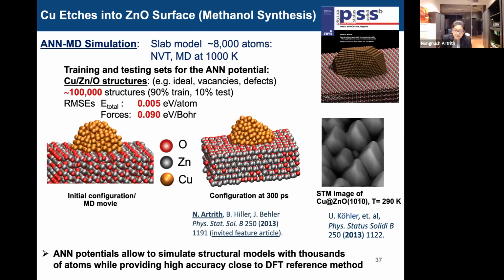So we used machine learning potentials, or neural potentials, to simulate a copper nanoparticle on zinc oxide with around 8,000 atoms in total, like you can see here. Actually, this would not have been possible with only DFT methods. Our simulation showed that the copper clusters sink into the zinc oxide surface and form a pyramidal shape, like you can see here. This is also in agreement with the STM images from our collaborators.